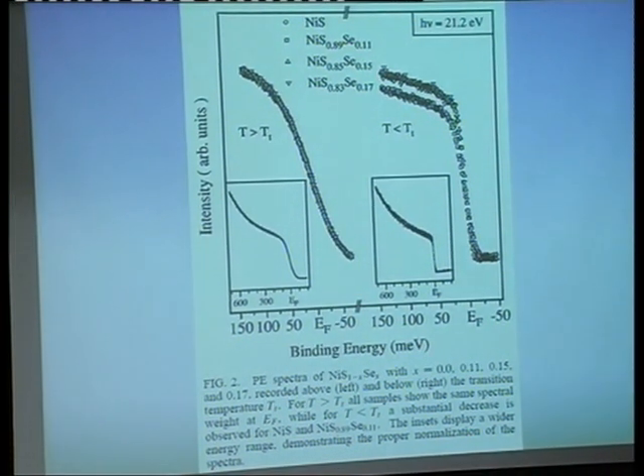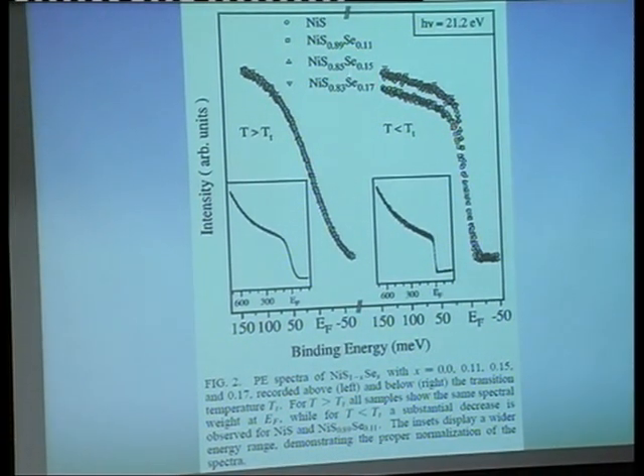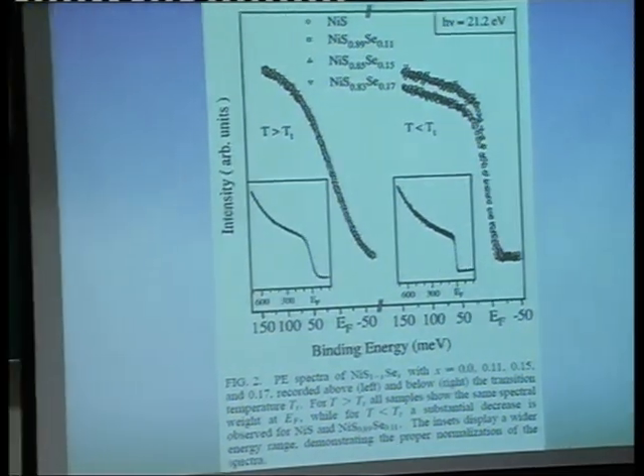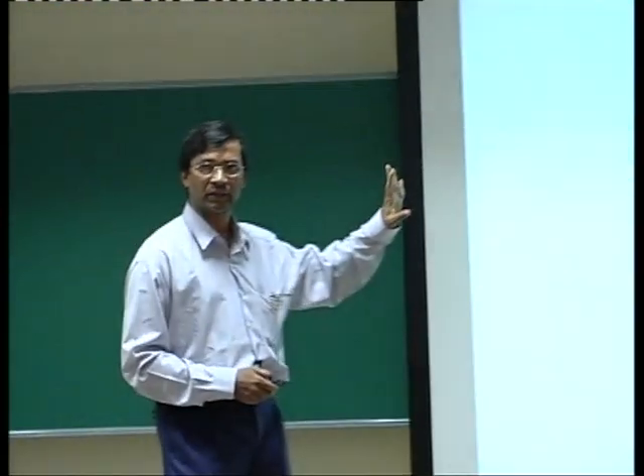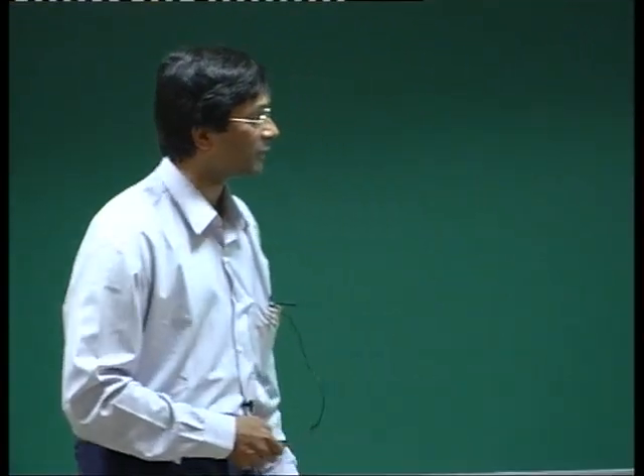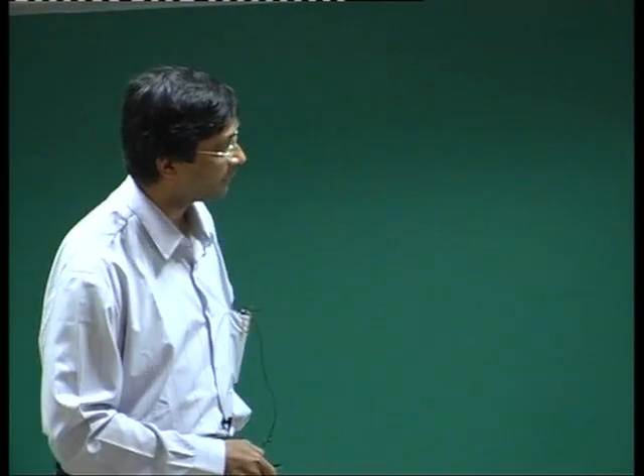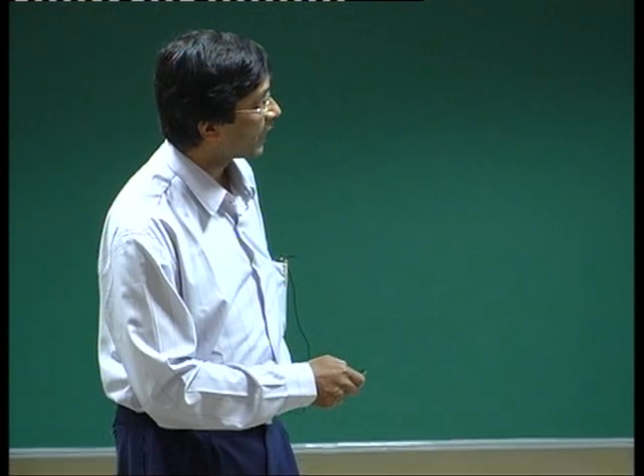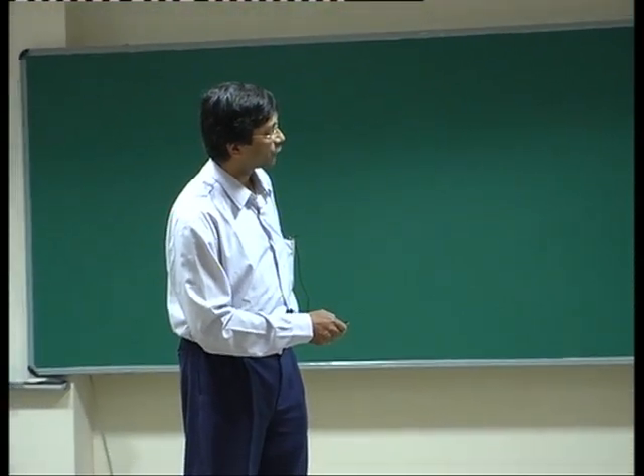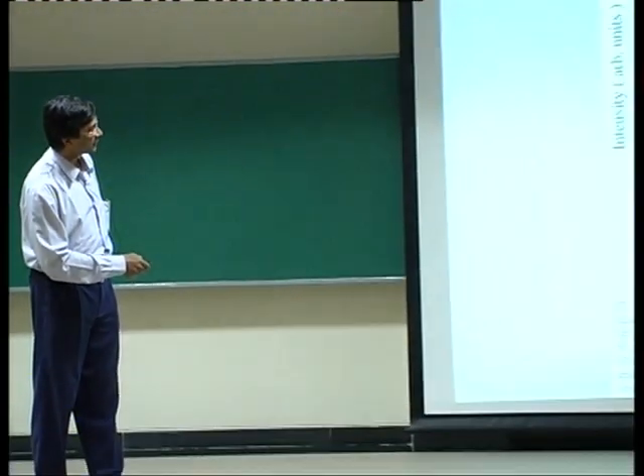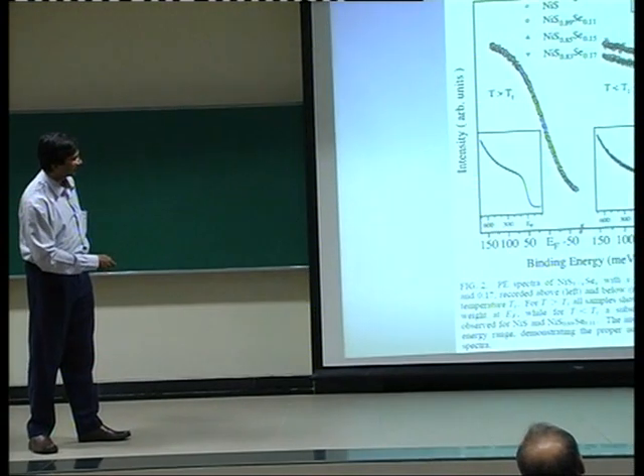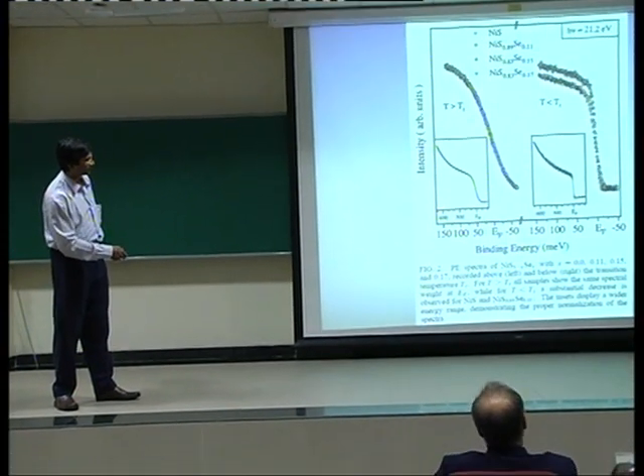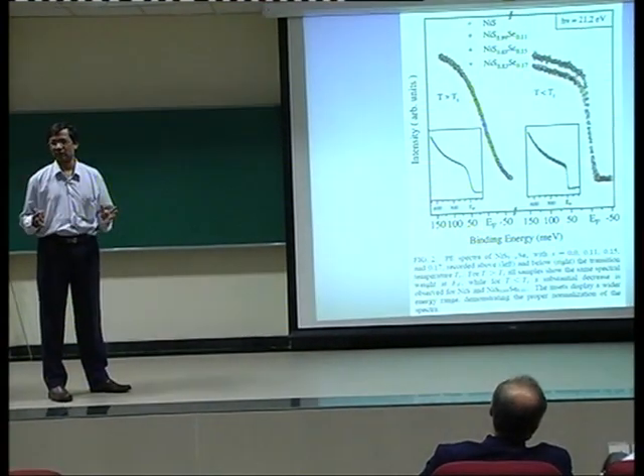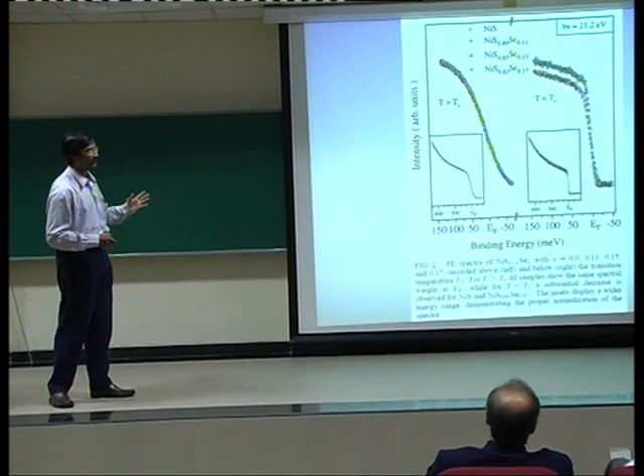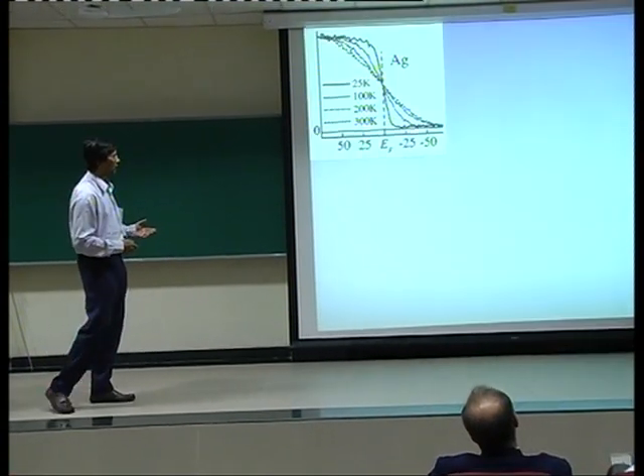These two will remain in the same state as here as I lower the temperature, so that I have a good reference at the low temperature, and I don't have to do the jugglery of taking into account the Fermi-Dirac statistics distribution separately. And those immediately find that at low temperature, these two that show a transition separate out from those which don't in this energy range, but not in this energy range. Showing that there is something happening across the transition. It's not that nothing is happening. Something is happening, but what is happening, that is what we try to understand.